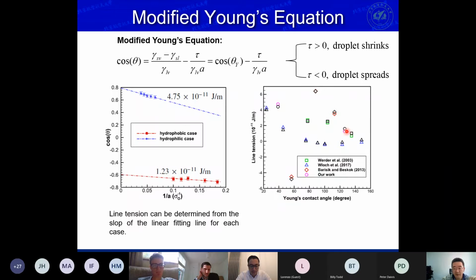Here, this one and this one are our data, and we also put the data from the literature in this figure. As you can see, the data of the line tension are so scattered, even where the data are for water droplets on surfaces. So it means that the line tension is so sensitive, and maybe there are some reasons we need to figure out. One possible reason is that in the modified Young's equation, the surface tensions are from planar surfaces, and we know that the curvature has some effect on the surface tension.